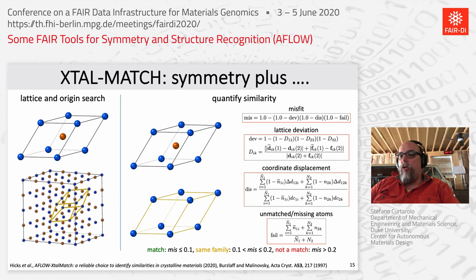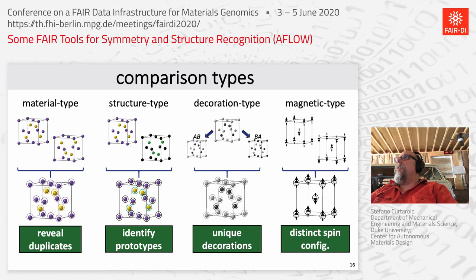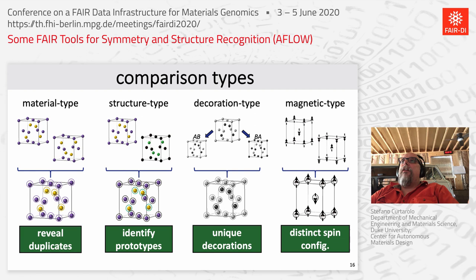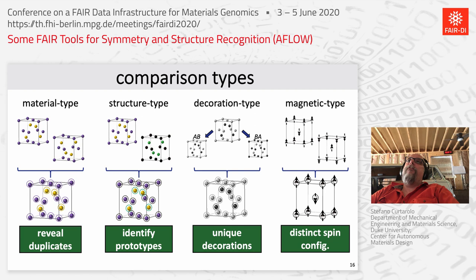You match in terms of misfit: the number of atoms matched, the number of coordinate displacements, and the lattice deviation. You take a quadruplet of origin plus three atoms and try to match them. If the misfit is small they are the same; if large they are completely different; if in between, they are the same family but distorted. Comparison types include material type, structure type, and decoration — whether blue and yellow atoms form the same rock salt regardless of labeling.